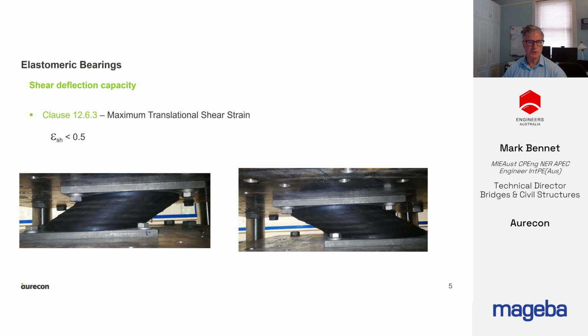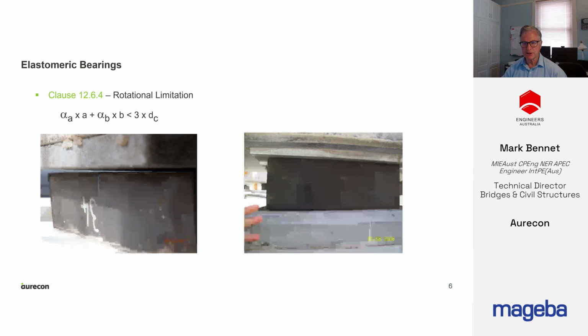The shear deflection capacity is set with a maximum shear strain of 0.5, which corresponds to half the total rubber thickness of the bearing. However, for infrequent loads, elastomeric bearings have a much larger shear deflection capacity, as demonstrated in this graph. Therefore, clause 12.6.3 states that brake and earthquake forces need not be considered for the application of the shear deflection limit.